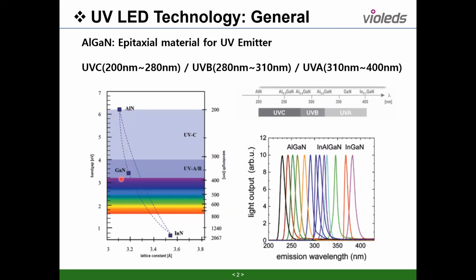Another thing that you must understand is that ultraviolet means very high energy, and when the hole and the electron recombine, there should be direct recombination. It means that there is no other energy layer between them. So that's the difficulty of making the UV LED, and that's the reason that even though the blue was made 20 years ago, the UV efficiency is still very, very low.